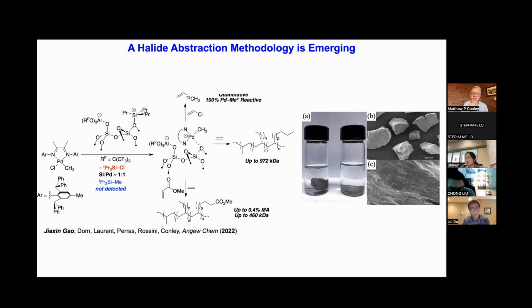I will also note, I kind of left this off the slide because it's a detail, but since you're bringing it up, these are actually bimodal molecular weight polymers. So I'm showing the higher molecular weight fraction, which is the predominant fraction in the material product, but we also generate a very low molecular weight fraction as well. So some of these palladium sites are prone to doing your classical alkyl transfer chemistry, and some are not.